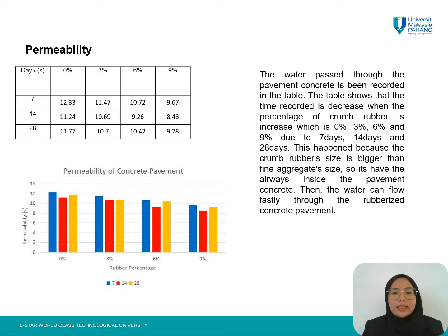Then for the permeability test, the time for water to pass through the pavement concrete is recorded in the table. The table shows that the time recorded decreases when the percentage of crumb rubber increases, which is 0%, 3%, 6%, and 9%, for 7 days, 14 days, and 28 days. This happened because the crumb rubber size is bigger than the fine aggregate size, so there are airways inside the pavement concrete. The water can flow fast and easily through the rubberized concrete pavement.